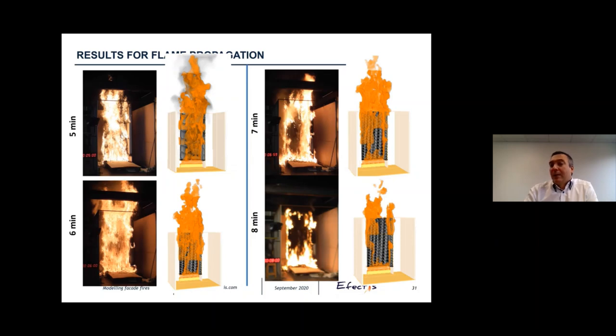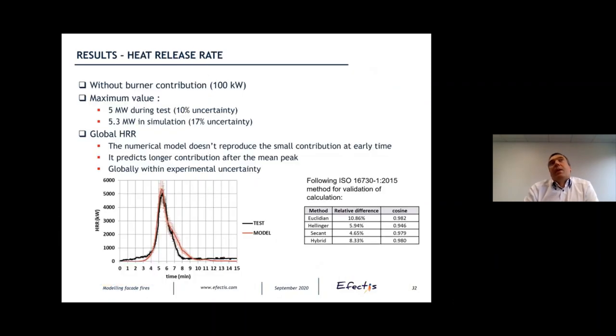and it means that the material that is driving the fire at this step disappears quickly. These results, what I mentioned, are valid at the scale at what we test, but they are valid for validation of the model. They are not directly extrapolable to other scales. So it's just a kind of comparison that we could have. We validate the model. It gives us also additional information, like the relative contribution of the different materials that cannot be catched experimentally. So we cannot experimentally say, okay, this material is contributing in that proportion, this one is that other. It's impossible, but with a model we can. We can have also other details like temperatures in depth and so on, so that are difficult to measure sometimes.